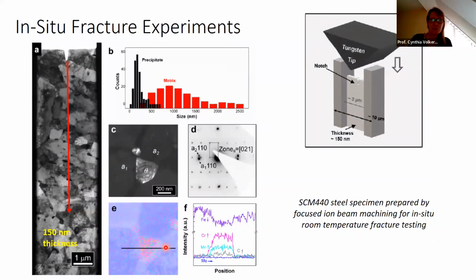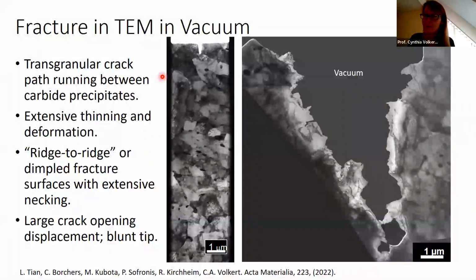And you can see here on the left a microscope image of the cross-section of a specimen that's been prepared and is ready for a TEM fracture test. So it's this lamella thickness you see here. We've been able to do various things like identify carbides, and get grain sizes and precipitate sizes in the material. And then we go in and we fracture this with the method I described. First, let me show you what it looks like beforehand and what it looks like afterwards. So at the beginning, we have the structure you already saw. And afterwards, it looks like this. This is after it's been pried apart.